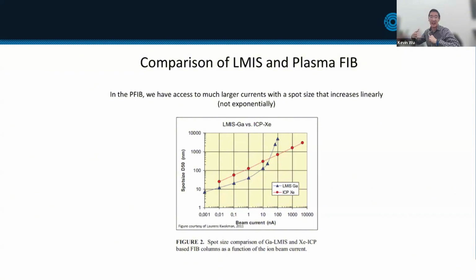And then moving forward, when you actually image your sample, you also want to keep your electron beam dose very low. So very low beam currents and accelerating voltages, so below 3 kV or so, and maybe 50 picoamps or less. And do frame averaging as well, which will reduce the dwell time of the electron beam on your sample.